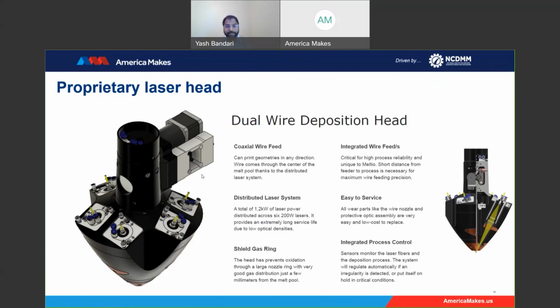And the best thing about this arrangement is that each laser can be independently manipulated. The max laser power is 200 watts, but you can assign any laser power to each of the lasers. So this makes me imagine melt pool shaping. That means you have these 6 spot sizes, and you can assign different laser powers to each one of these. Essentially, you are fiddling around with the heat distribution around the melt pool. I know a lot of customers haven't explored this option, but this is a very important feature when it comes to manipulating heat distribution around the melt pool.